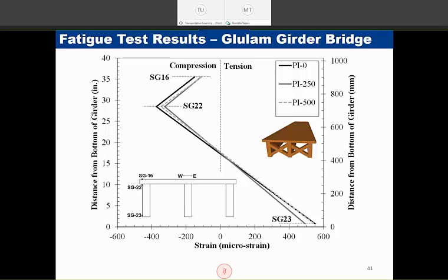In this slide, I'm showing the strain profile of the bridge. So it's essentially the strain value versus where we had the strain gauges along the depth of the bridge. It is clear that the strains of the deck were not compatible with the girder strains. Therefore, the glue lam girder deck section is not composite, and the glue lam girders should be designed as a non-composite section, fully non-composite. So that was one of the big conclusions out of this fatigue testing for this bridge.